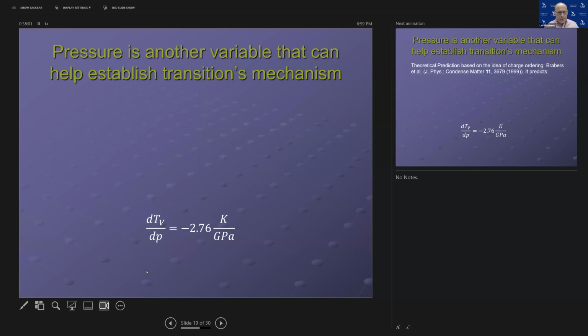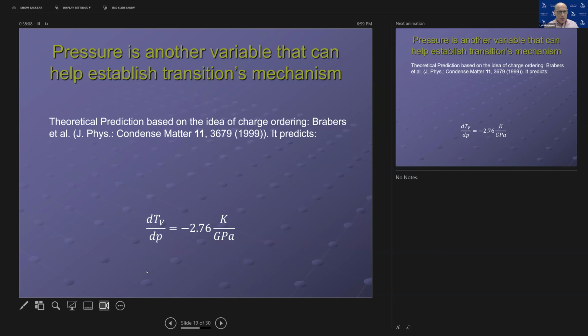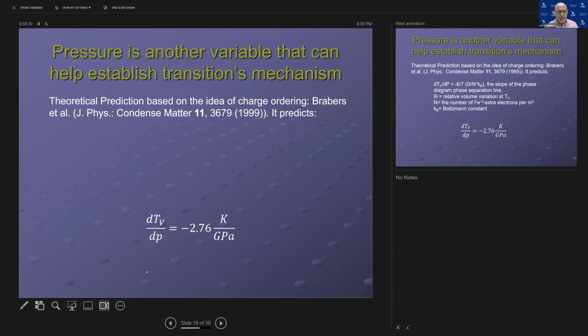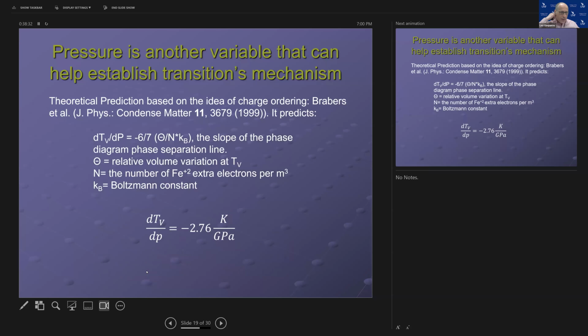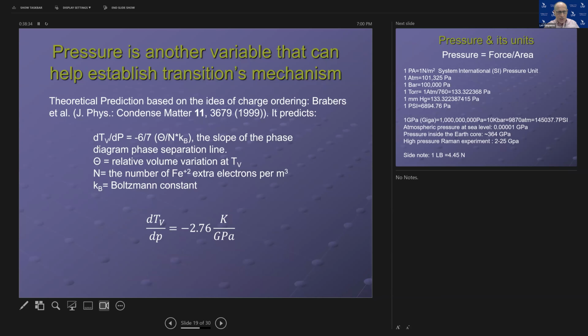Why am I interested in that? Well, pressure is another variable that can establish the mechanism of the transition. There is a theoretical prediction that is based on charge ordering. And there was a long dispute over whether there is charge ordering there or there is no charge ordering. One of the theoreticians came up with a model, and that was a testable model. In other words, what he proposed was that the slope of the phase diagram, the phase separation line, can be given by this number.